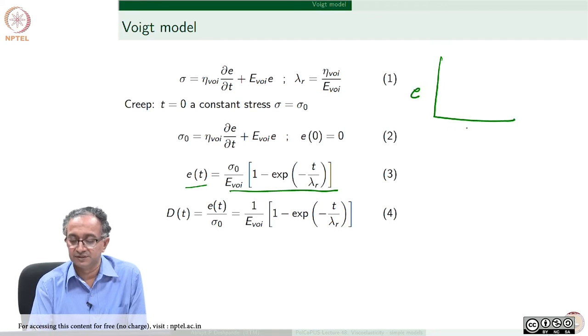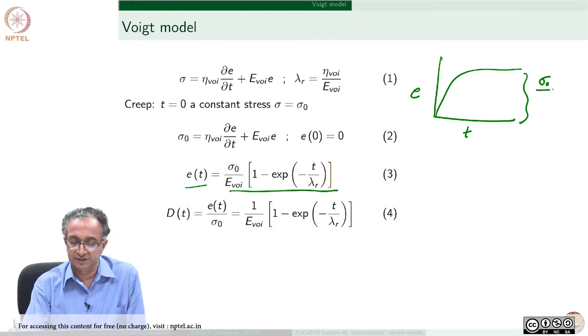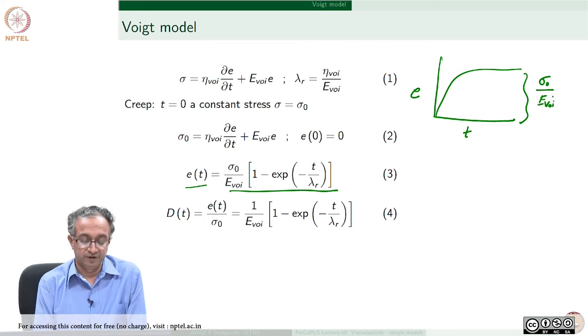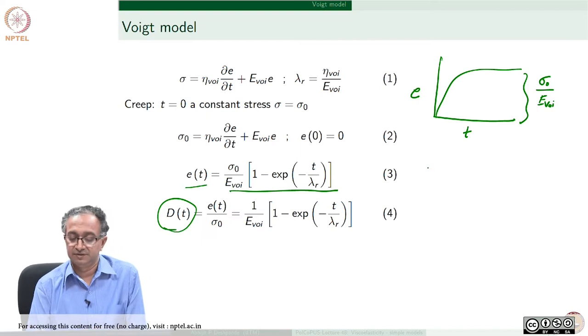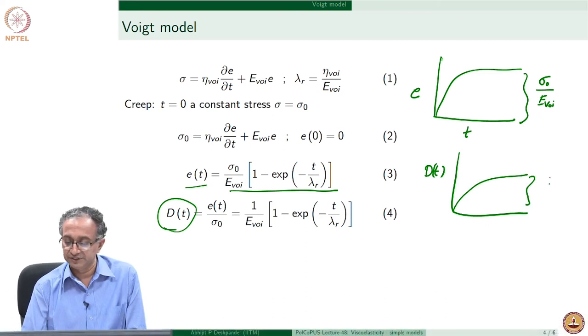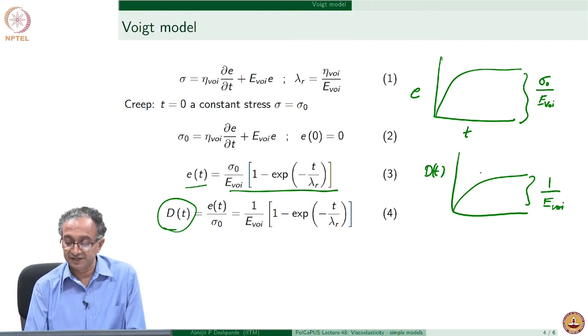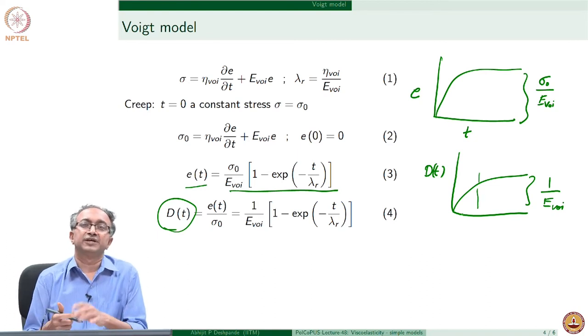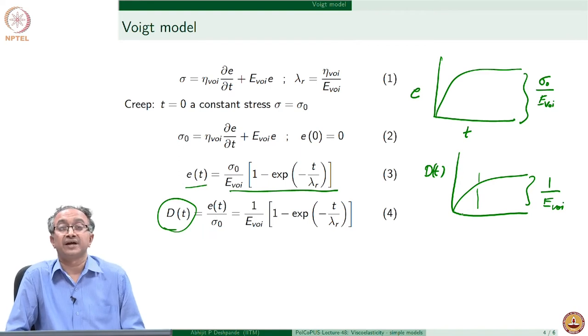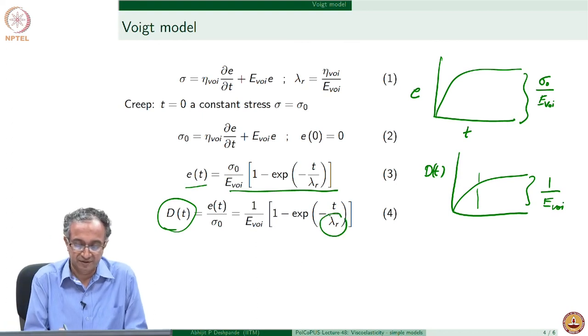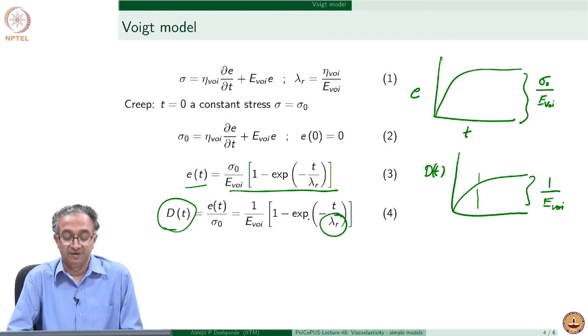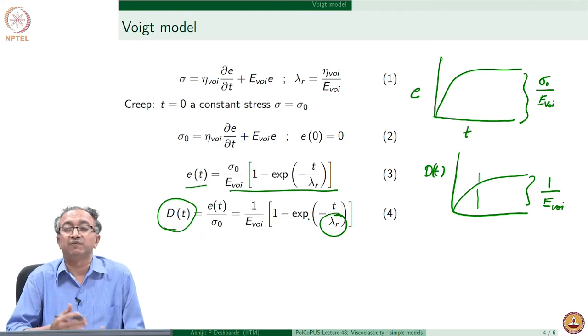This is the strain variation according to the Voigt model, and the constant strain value reached is σ/E. If we define the compliance as the response function, that is also an exponential function and the constant value reached is 1/E_Voigt. The time required to reach, say, 63% of the maximum value depends on the retardation time λ_r, which determines whether the increase in strain is fast or slow.